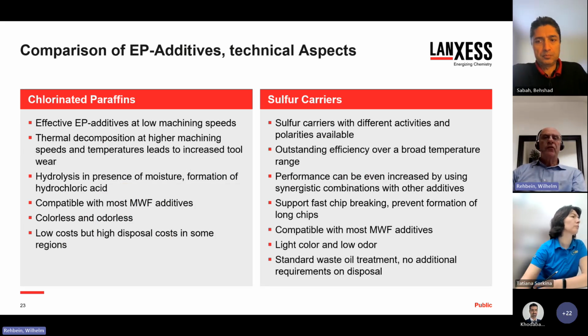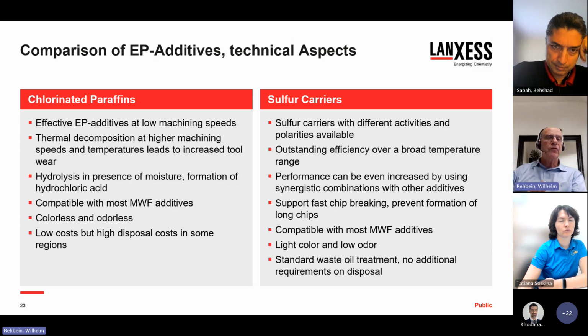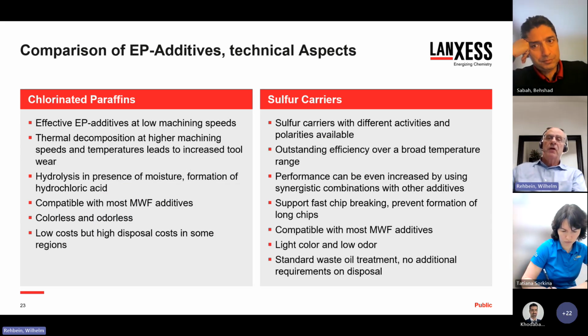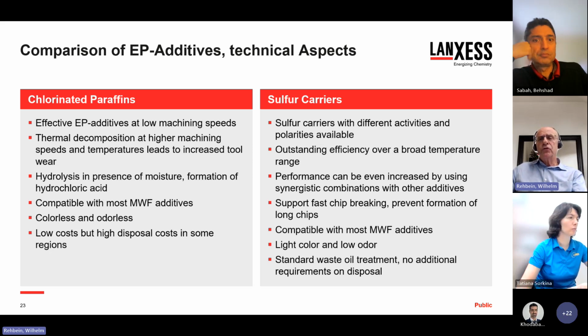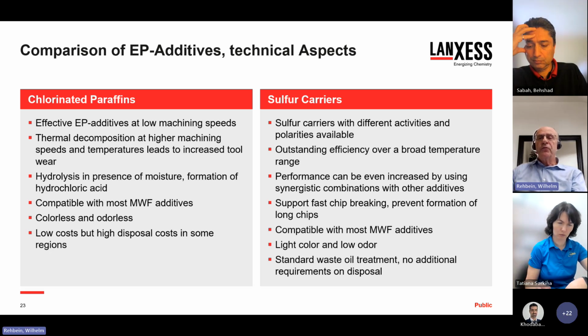So I will now come to a comparison of the technical aspects of chlorinated paraffins and sulfur carriers. And chlorinated paraffins are definitely effective EP additives at low machining speeds. But at higher machining speeds that are usually associated with higher temperatures at tool and workpiece, they tend to decompose, forming hydrogen chloride, which has a strong negative effect on the tool wear. And in presence of water or moisture, chlorinated paraffins tend to hydrolyze, forming hydrochloric acid that can corrode the tool, the workpiece, and the entire machine tool.